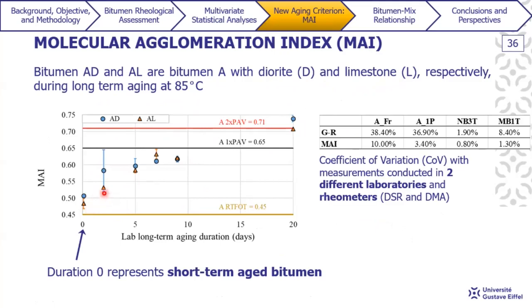So here we can see MAI versus laboratory long-term aging duration in days. We can see an increase, and apart from this one here, the dispersion is not that big. So we can see an evolution of these values here. And these lines here represent the MAI value for RTFOT aged bitumens, and also 1 and 2 PAV aged bitumens.